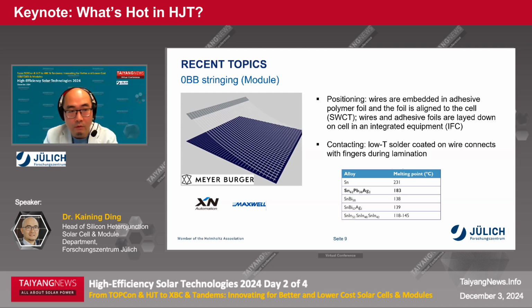Here I just put one example, which seems to be the most favorable solution at the moment, which is to use the SmartWire technology by Meyer Burger, where the positioning of the wire is done by embedding the wires on a polymer foil before you make the module. And the wire is coated with a low melting point solder alloy. So the contacting happens during the lamination, where the temperature during the lamination will melt the solder alloy and connect the wire together with the fingers.